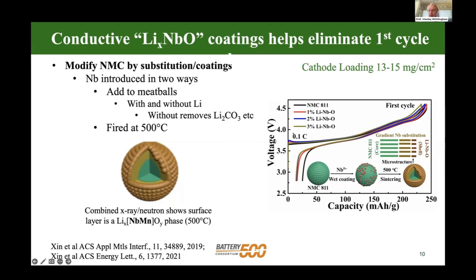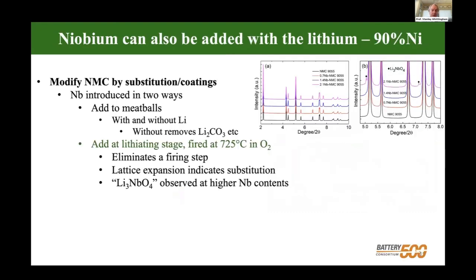And if you look at this plot on the right, you can see as soon as you put a little bit of niobium in there, it doesn't matter whether it's 1% or 3%, it makes no difference. We're almost eliminating half of this first cycle loss. So modifying the surface can get us back this capacity. And what we think we can do is get it all back by doing the appropriate modification. But the other option is to actually heat it to higher temperatures.